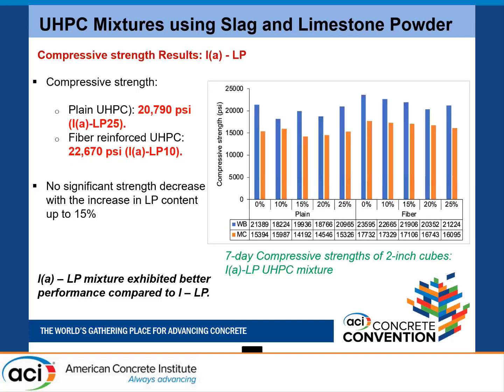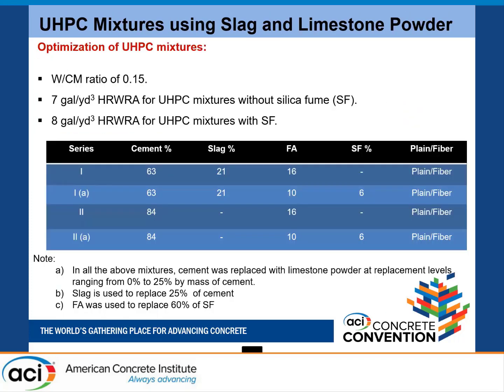And if you look at it, the compressive strengths of plain UHPC and fiber UHPC here are 20,000 to 22,000. We got increased compressive strengths here, but we have seen no strength decrease with the limestone powder cement combination with slag. And here the limestone powder is replacing cement by 15%.